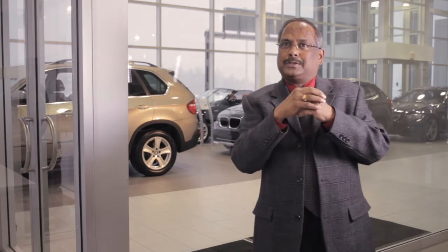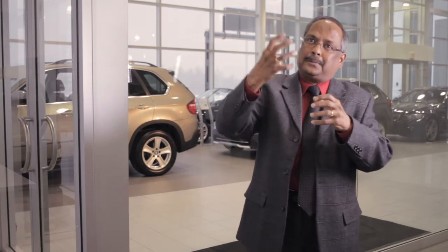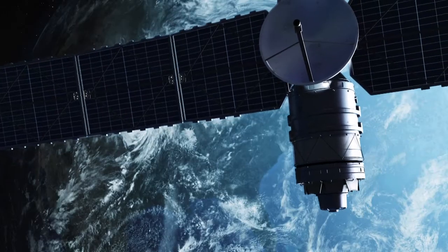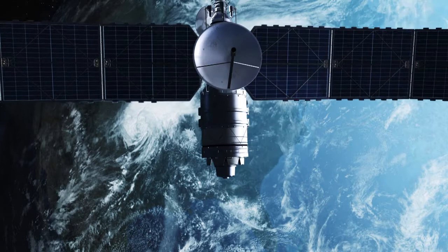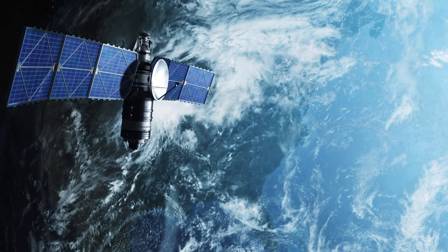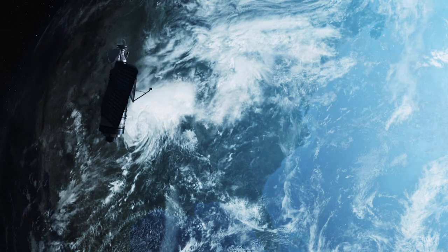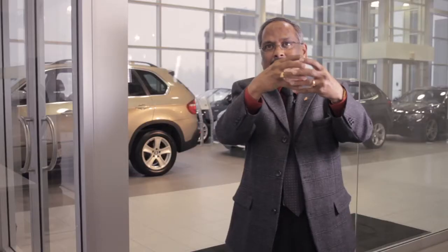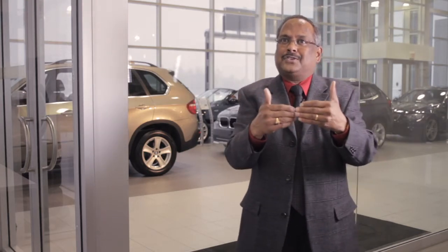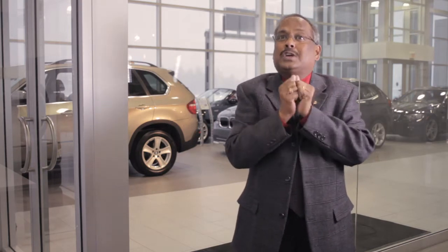There is another application for another kind of thin film that we are producing in the laboratory. If satellites are covered with the kind of thin films that we are proposing, the moment the satellite is exposed to the sun, intense heat radiation is hitting it. Very soon the temperature gets to the transition temperature, and it starts rejecting the heat. And the moment it goes in the shade and the temperature falls below this transition temperature, again there is absorption, so it keeps the heat to itself.